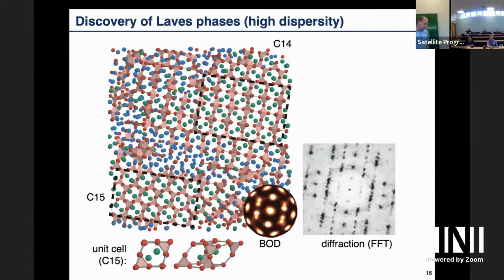There are two possibilities. Either this is not fully relaxed yet, and it's a crystal in the process of forming, and if I wait longer, eventually this will just grow and fill it. Or the tails of your distribution have to go. That's the second possibility, that you just argue, well, I have some waste. If I take all the small particles out, all the large, and the stuff in the middle or on the tail, I put it aside.